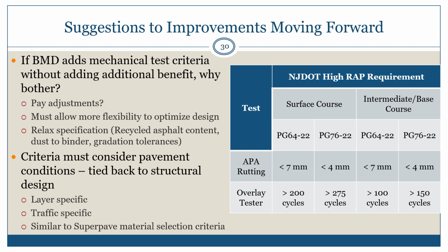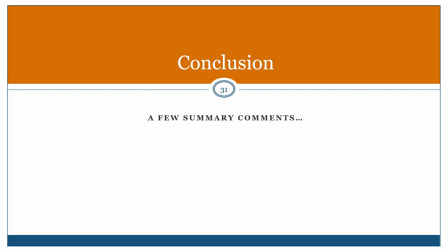You can see an example from the New Jersey Department of Transportation on their high RAP specification where they do require different levels of rutting, whether it's a neat binder on a lower volume road or a polymer modified binder on a higher volume road. And also that criteria is dependent on whether it's in the surface or the intermediate and base, both for rutting and cracking. So tying it back to our structural design is very important to be consistent with our current Superpave system. A few closing comments to tie a bow around this presentation.